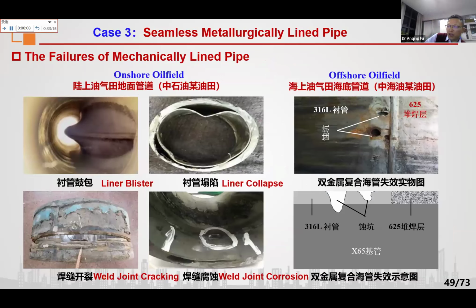However, we have already found a lot of mechanical lined pipe failure cases, no matter in onshore oil field or offshore oil and gas field. All the failures shown here we collected from the oil and gas field. The first one is the liner blister. Since there is no bonding strength, usually due to the pressure fabrication, sometimes it will lead to the liner blister. And second one is the liner collapse. The third one is weld joint cracking. The last one is the weld joint corrosion.